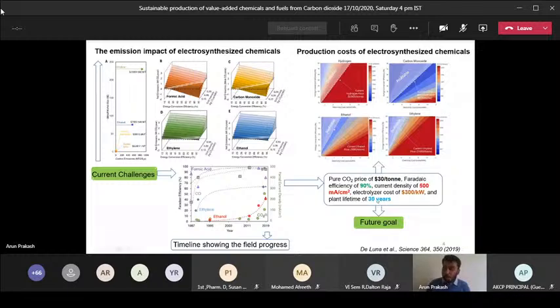For instance, a pure carbon dioxide price of about $30 per ton, a Faraday efficiency of 90%, a maximum current density of 500 milliamperes per square centimeter using an electrolyzer built at a cost of $300 per kilowatt, and a plant lifetime of 30 years. This is a huge goal, and we have to focus on it, and we have to construct such a water electrolyzer or CO2 electrolyzer to produce these value-added chemicals.